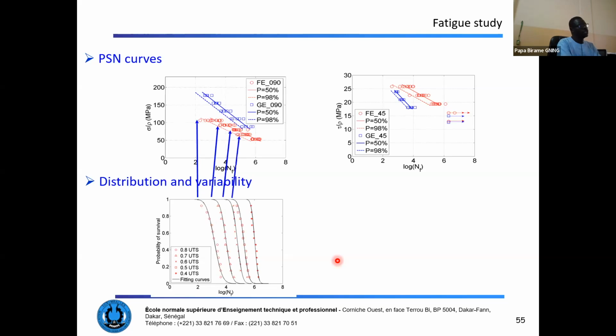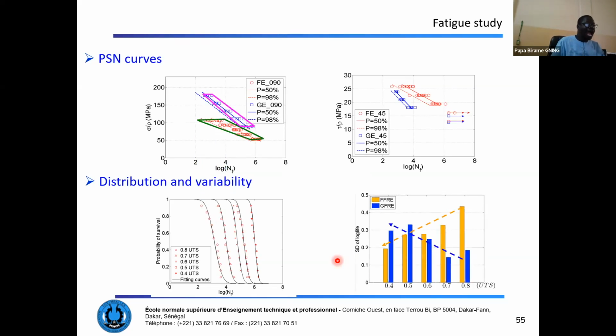We can see also that as the flax fiber composites are loaded, their variability, the scattering, is diminished. And the more you load the glass epoxy composite, their scattering increases. This is favorable to the flax epoxy composites. That means that with the increase of the loading cycles, the scattering is diminishing, and we have a better prediction of the behavior of the flax epoxy composites.